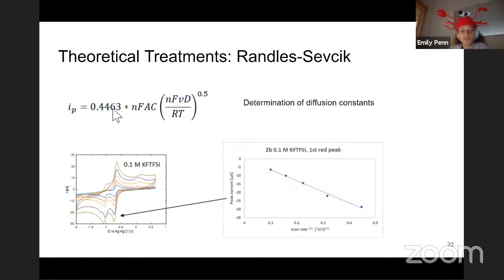Another theoretical treatment that can be used is the Randles-Sevcik analysis. I'm not going to walk through the derivation at all, but this is an equation that is used to determine diffusion constants. This equation relates the peak current as a function of scan rate. If you do a CV at multiple scan rates, you can plot the peak current versus the scan rate to the 1/2. By looking at the slope of that line, all the other things in this equation are constant. We have the number of electrons transferred, Faraday's constant, area of your electrode, your bulk concentration. The only other constant that we don't know is the diffusion constant. So by doing this, you're able to determine the diffusion constant for different molecules.